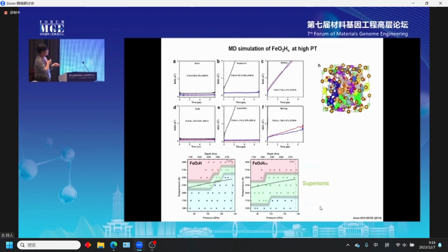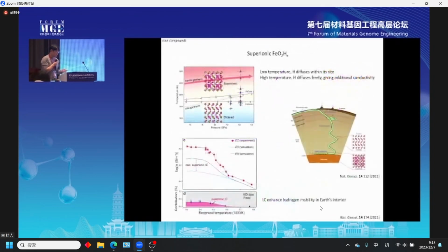And at the time, we completed the phase diagram with pressure and temperature, with a certain region in the middle, between the solid and the melting. And we proposed that superionicity can exist theoretically, and people were not actually convinced. So we combined with experimental data two years ago. Experimentally, my colleague Qingyang Hu measured it. So this is the experimental data.